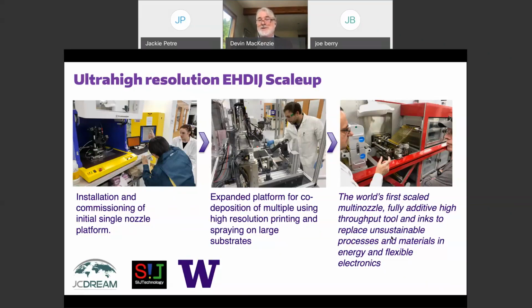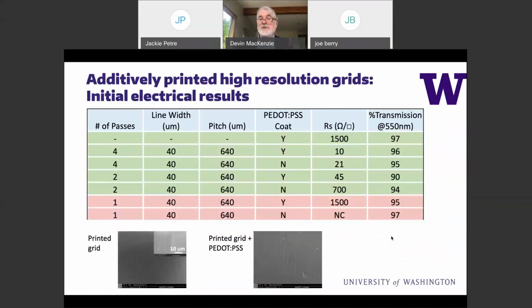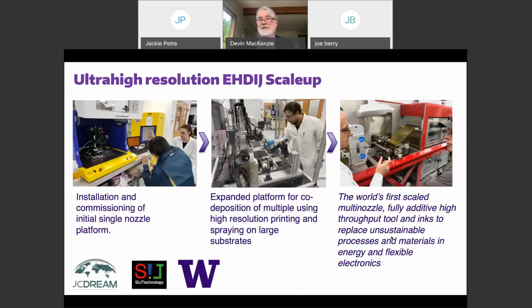Why? Because the great news is we're printing a micron at a time. The bad news is we're printing a micron at a time. It takes a long time to make a centimeter out of a micron, unless you can print a lot in parallel. And so the idea for conductors in inkjet is simple: electrodes. We essentially need an array of single nozzles blasting away at the right pitch, continuously depositing lines to make our transparent conductors. So we're demonstrating that for the first time in a roll-to-roll.